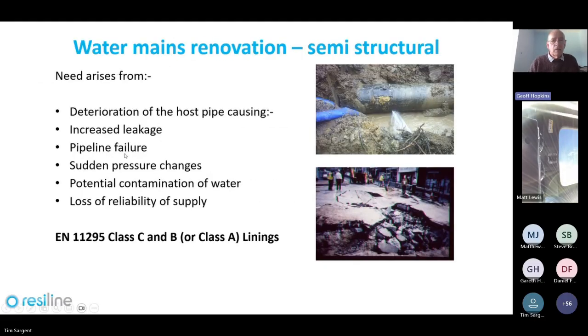Here we are. Not all pipes are in fundamentally sound condition. You've got this vast amount of pipework in the grey area in the middle, where they're what AWWA would term partially deteriorated pipes. There's still fundamentally good residual strength in the actual pipe wall, but it's not hydraulically sound. It's got leaks on it. It's subject to failure. You've got holes rotting through the pipe wall, and in those conditions, this is really probably the sweet spot for spray lining. You want to apply a semi-structural lining.